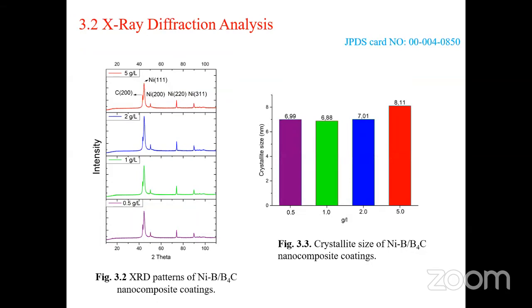X-ray diffraction analysis. The XRD patterns for the nanocomposite coatings are shown in figure 3.2. The XRD patterns show typical peaks corresponding to the 111 plane of nickel coatings according to the JCPDS card number. Especially, the peak intensity in the 111 plane in the nickel boron alloy coating is higher than the other coatings. With the addition of boron carbide, while the peak intensity of the 111 plane decreases, the peak intensity of other planes such as nickel 200, 220, and 311 increases.